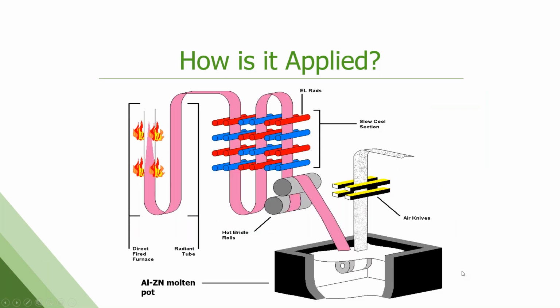This is a little bit of a close-up of what we call the process area where the real work is getting done in the line. This is an example of a direct fired furnace. So you actually are impinging the strip with flame inside the furnace. Helps anneal it, helps clean it, also helps to anneal it to the properties it needs to have mechanically. These radiant tubes are doing that work as well. It's heating the strip and cooling the strip before it enters the pot. And this is what the inside of the pot looks like. There's a giant roll that the strip rolls down underneath and then comes back up, back through the air knives to control coating weight or thickness of metallic coating that's been applied.